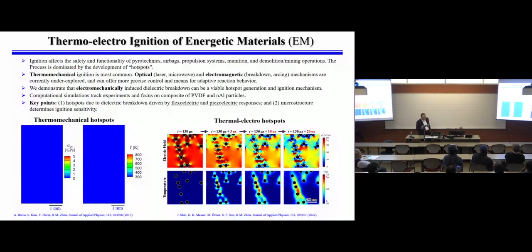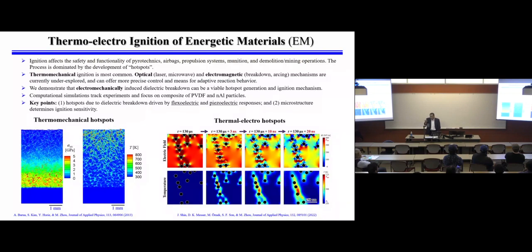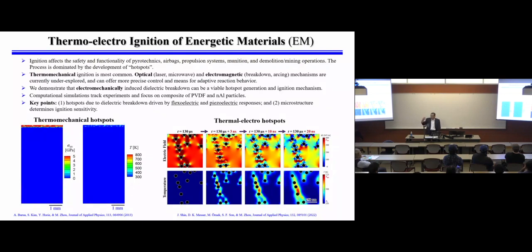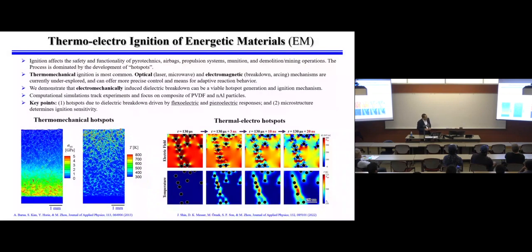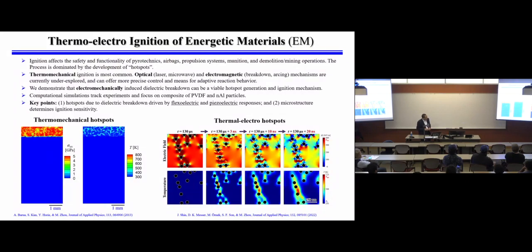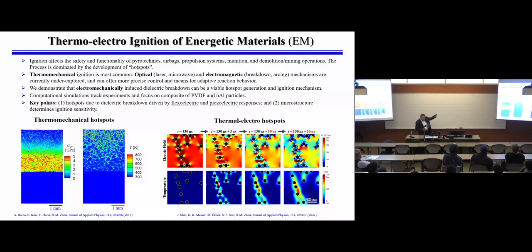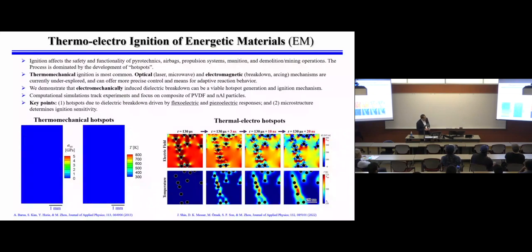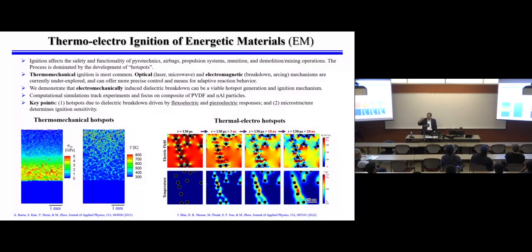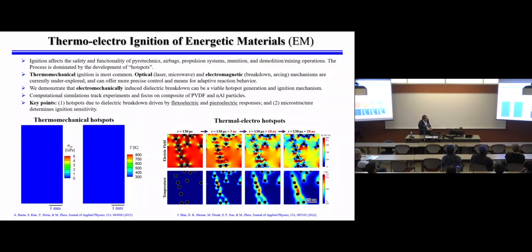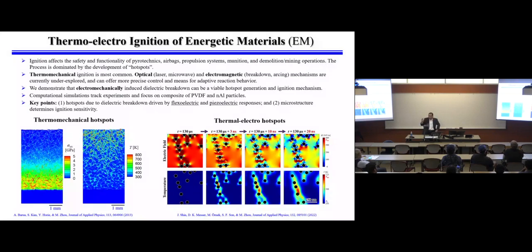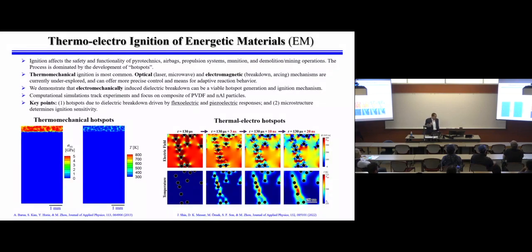Energetic materials are typically used in mining, demolition, airbags, and of course munitions, because you want chemical energy release. Now, the historic way of activating the reaction is by applying a mechanical force. You impact it, you apply a mechanical pulse, and then mechanical deformation generates plasticity and friction that causes so-called hot spots, the red spots there, which are high temperature areas where chemical reaction will initiate.